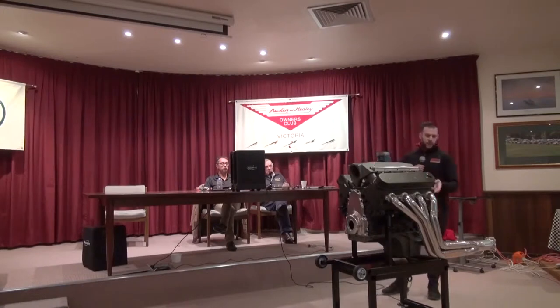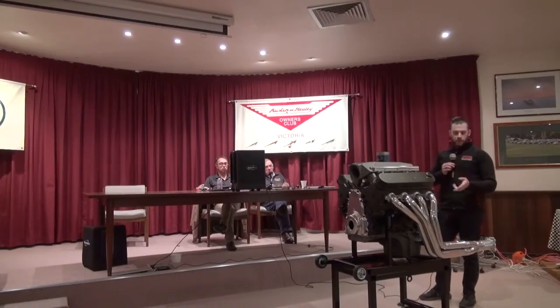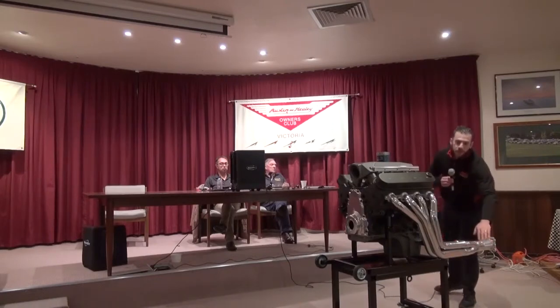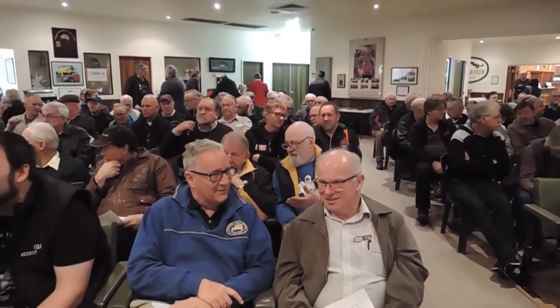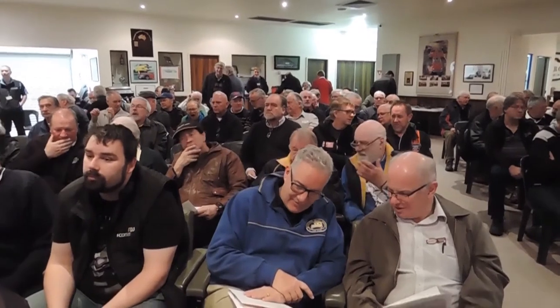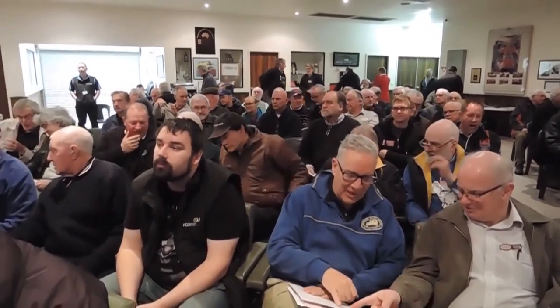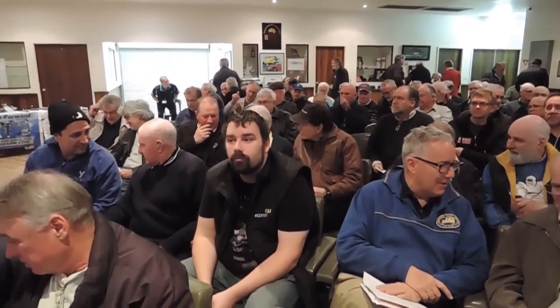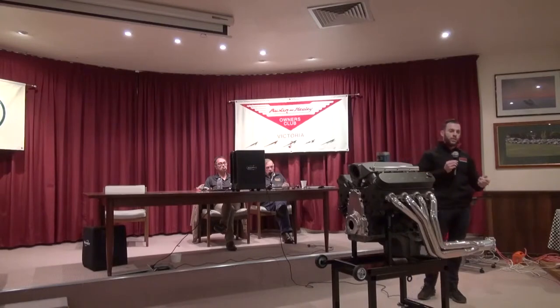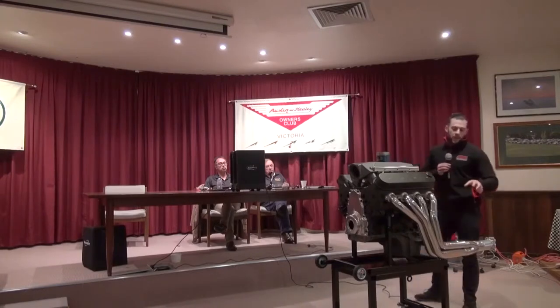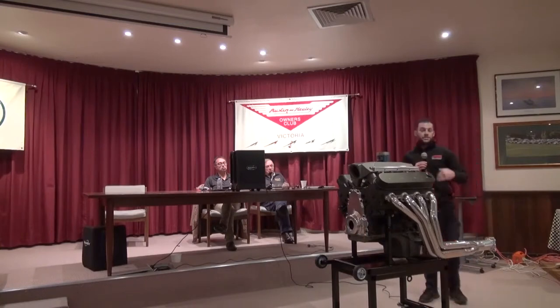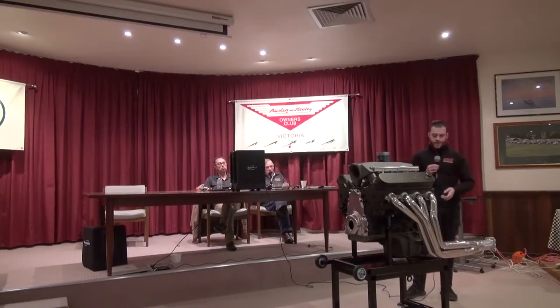So with the ceramics that you see in front of you here, we have various colours you can choose from. Probably the most popular that you've seen around is the black and the chrome. Both have different capacities with the temperature ratings. Chrome is an 800C rating. Someone here probably has ceramic coated heads in polished. Once it gets up to a certain temperature, it breaks down the aluminium oxide in the ceramic, which gives it a galvanised, silvery dull look, which you may have seen before. So this will only have a rating of 800 degrees Celsius before it starts to break down. Once it breaks down, you will notice that galvanised look in the flux.